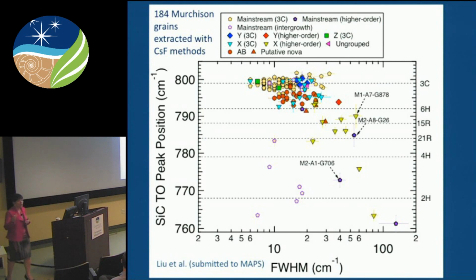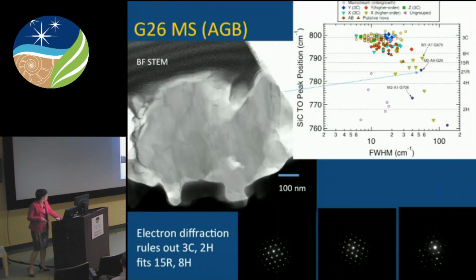You could even see the grains that were isotopically light in carbon were still consistent with 3C, but slightly shifted down in wave number. But there's a few of these grains, I think about 15 or so out of 184, which had a peak shift and shape that was inconsistent with a simple 3C cubic structure. And so I got involved at the point where we needed to determine what are those other crystal structures.